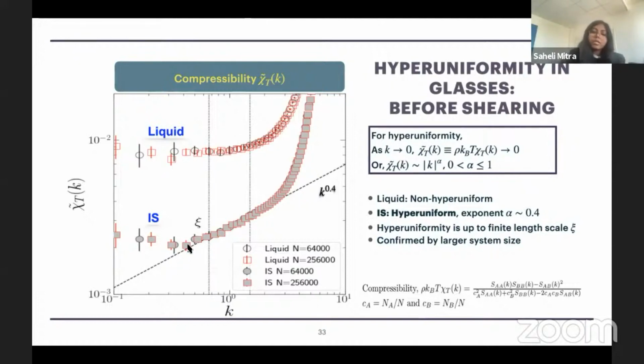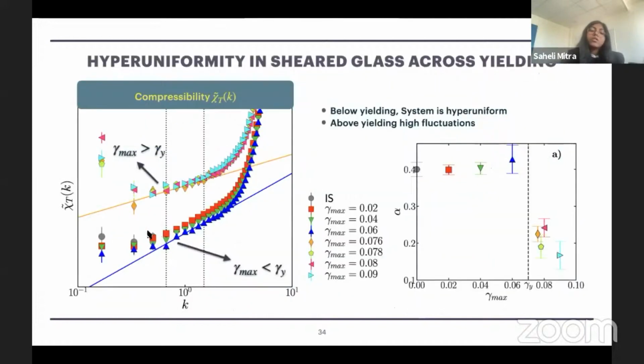Next, we see what happens to the system as we shear it. So we again compute the compressibility for different shear amplitudes across the yielding amplitude. What we see is below yielding, my system is hyperuniform and the exponent of the fit is close to 0.4. Above yielding, the hyperuniformity exponent alpha decreases dramatically, and we now have a non-hyperuniform system above yielding. Another interesting thing is in the low wave vector part, we see an upturn in the compressibility curves, meaning that there is strong fluctuation in the system.